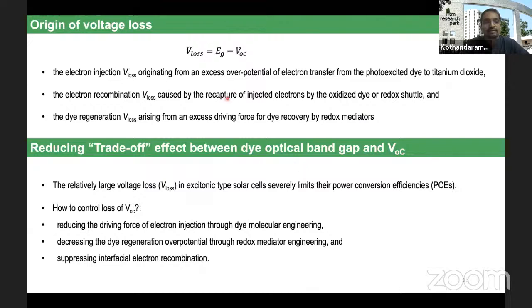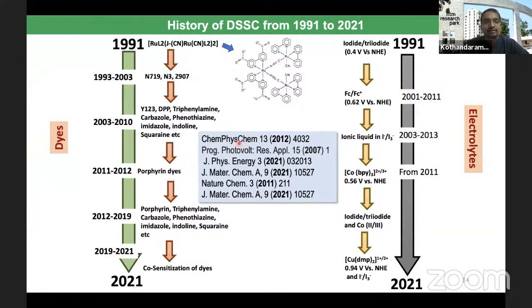So as I said in the previous slide, the voltage loss is basically the difference between the energy gap between the HOMO and LUMO and the open circuit voltage that we observe experimentally. This loss is contributed by three different processes: the voltage loss at the injection stage, at the regeneration stage, and because of the back electron process. So this voltage loss severely limits the power conversion efficiency of these dye-sensitized solar cells.